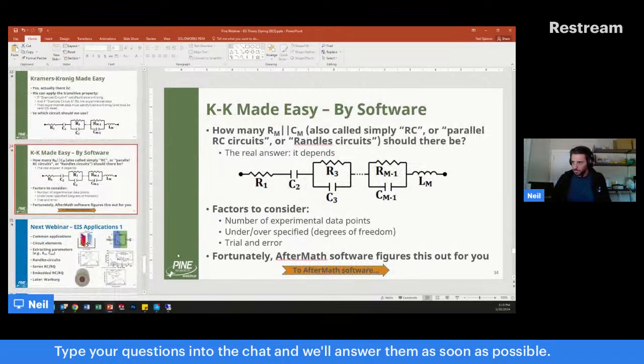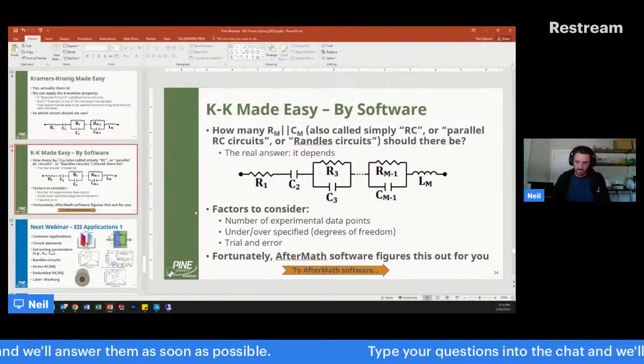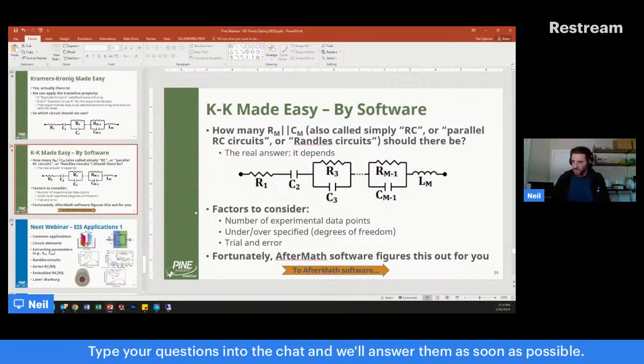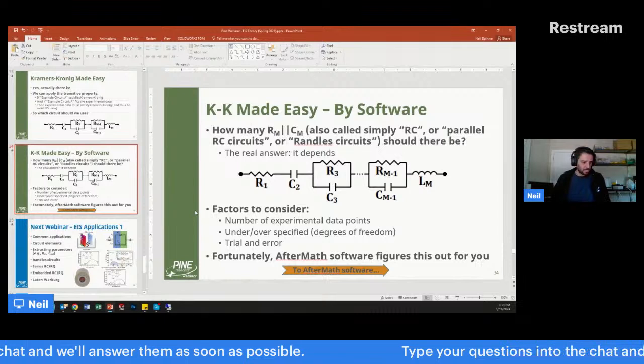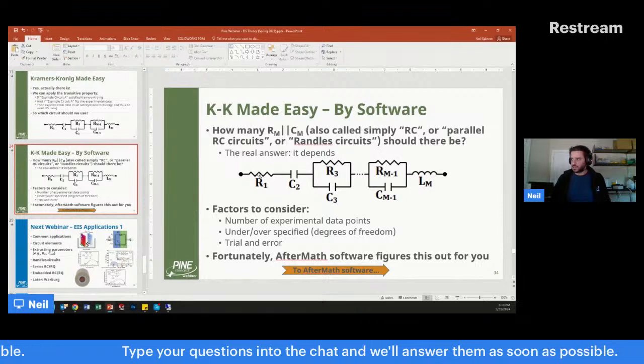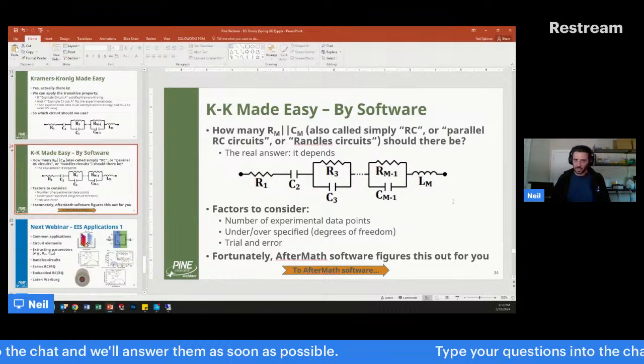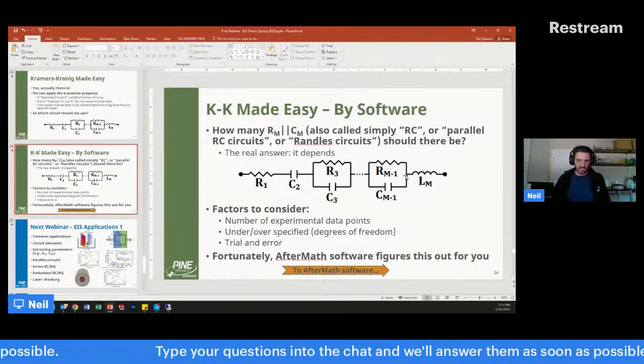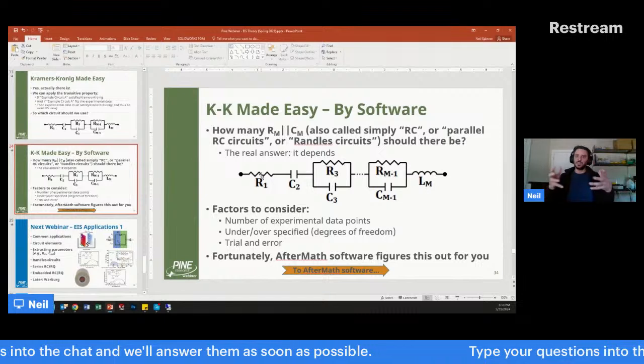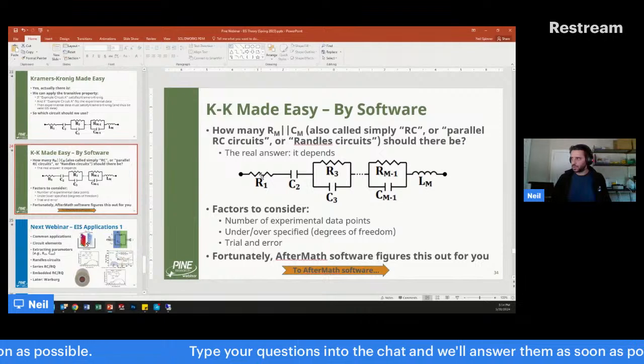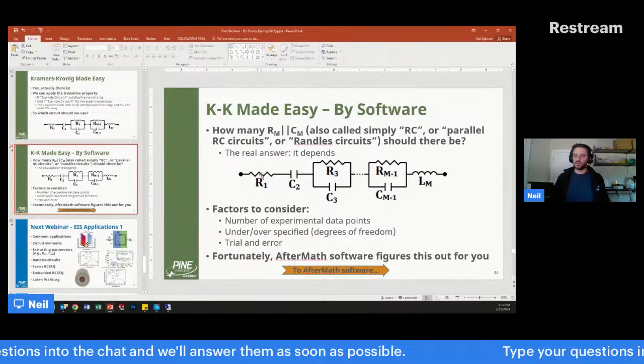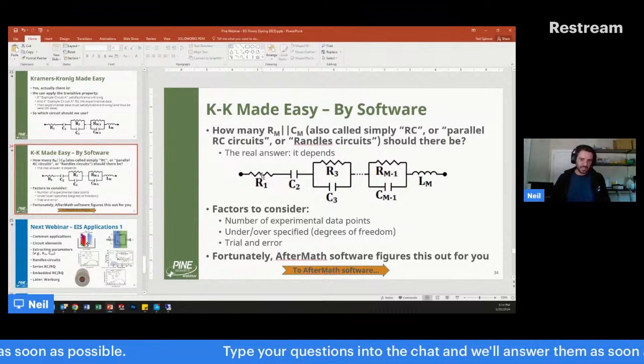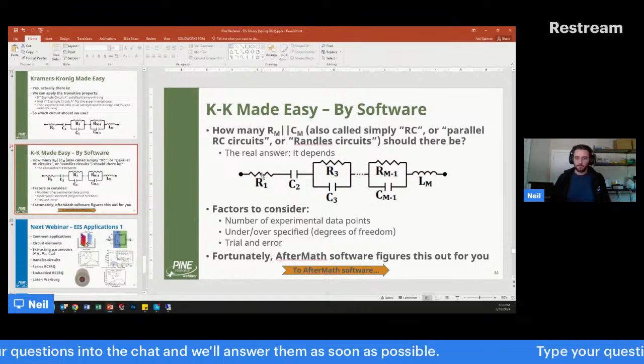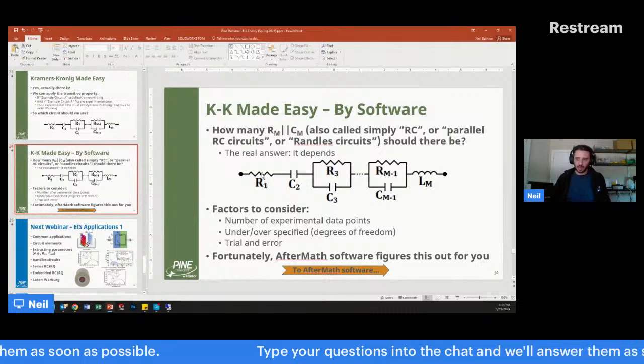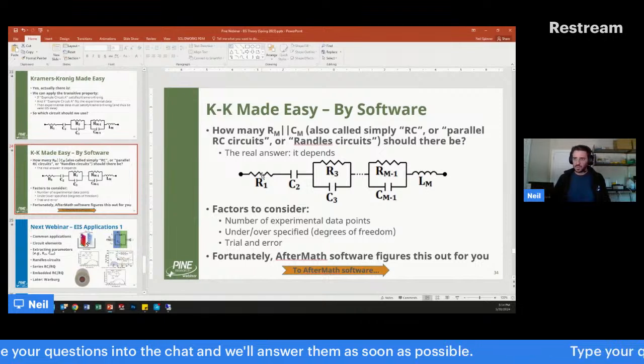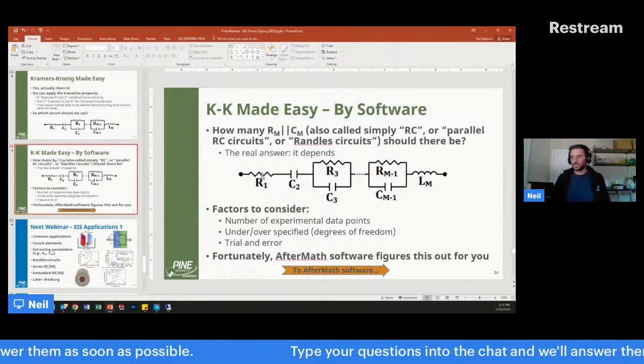That is what Dr. Boukamp proposed almost 40 years ago, and it has been used, to my knowledge, by every manufacturer and Kramers-Kronig algorithm, my company included. We fit this sort of infinite sum of resistors and capacitors and Randles elements and an inductor, and this circuit satisfies Kramers-Kronig necessarily because every ideal component by itself satisfies Kramers-Kronig, as well as any combination of those circuits. So in some respect, it is like a very convoluted circuit fit. But what it really is, is finding a way to fit the most like nth order polynomial to your data. And if it fits, then it presumes that Kramers-Kronig is upheld, or at least valid.